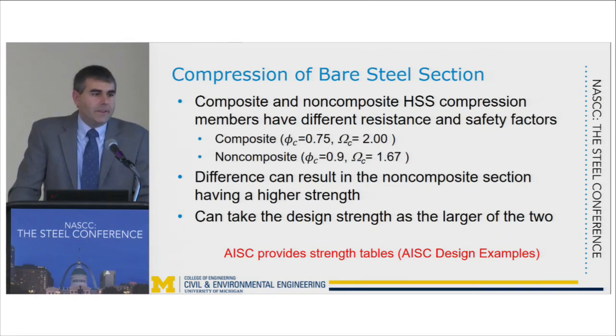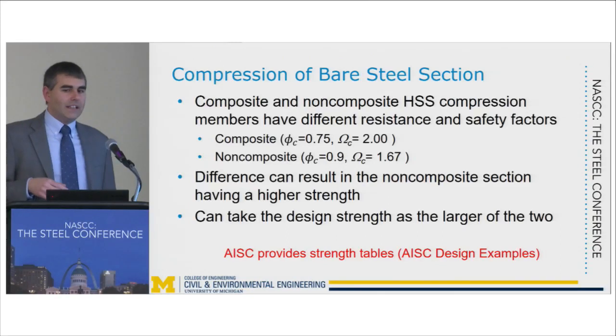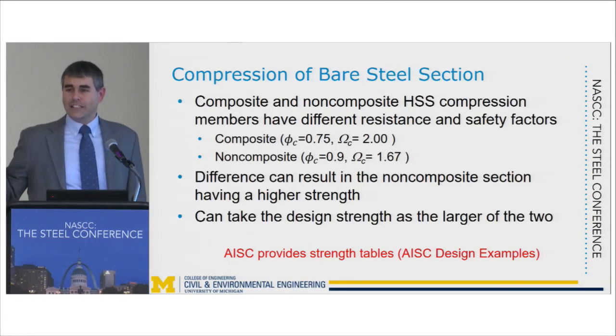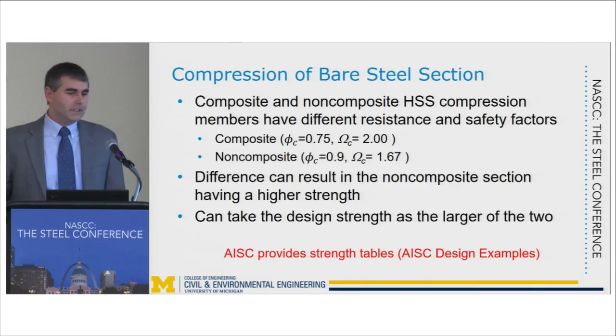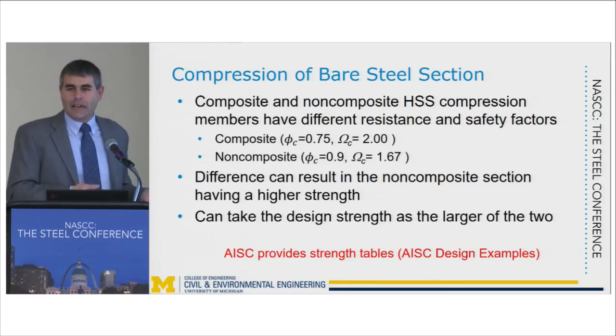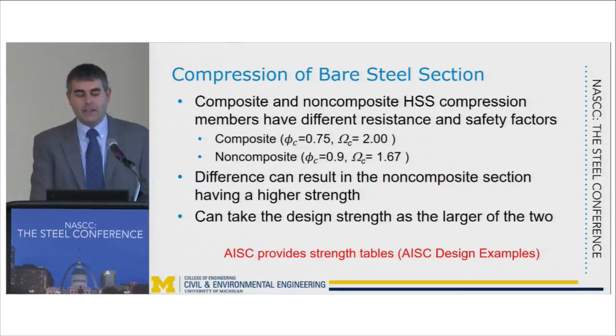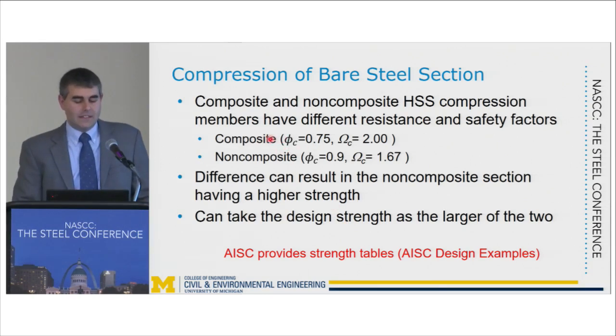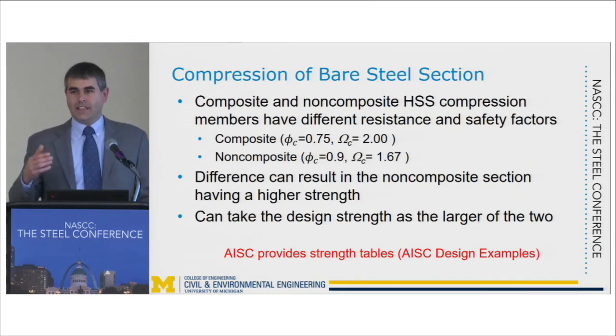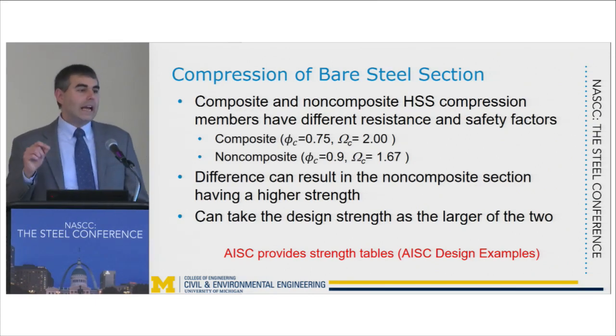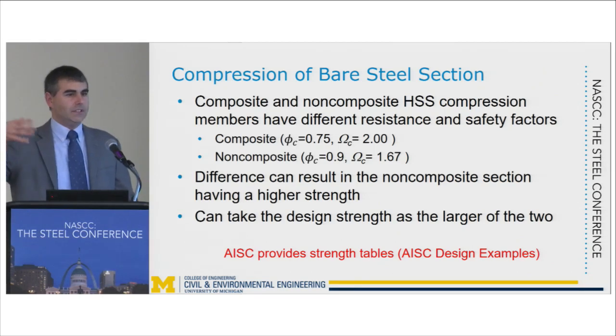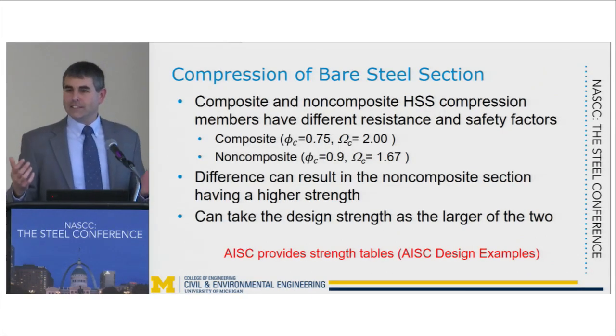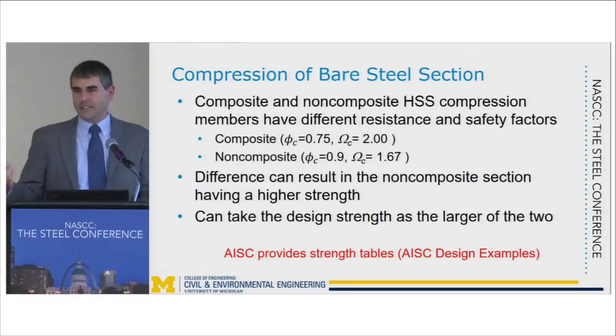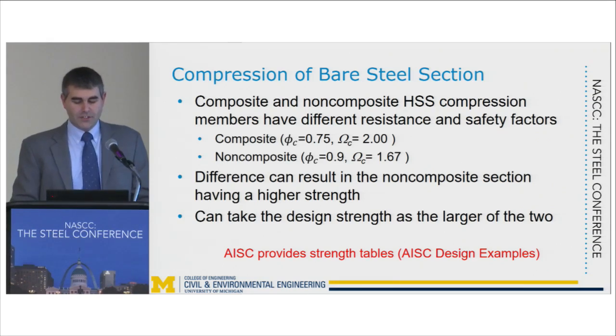The other thing you have to keep in mind if you're looking at the strength of a concrete-filled hollow structural section under compression is that you might actually calculate a case where the hollow structural section has a higher compressive strength than the concrete-filled hollow structural section. And you might say, well, how is that possible if we're accounting for the strength of the concrete? It really comes down to the fact that the phi factor we use for the composite section is 0.75, and for the non-composite section, we use 0.9. So you can end up with a case where the hollow section has a higher strength. In that case, you can use that higher strength from the hollow structural section as the strength of your member, but then you start to run into the question of whether it's actually worthwhile filling it with concrete because you don't necessarily need it from a strength standpoint. So just keep that in mind.